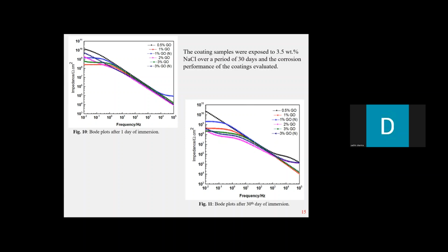And we can look at the 0.5 weight percentage. The values were well above 10 to the power of 9 up to 30 days of immersion. So overall, among all the coating systems, the 0.5 weight percentage GO, which exhibited approximately 85 degrees water contact angle, was the best, the optimum coating system, which exhibited the Z impedance value well above 10 to the power of 10.